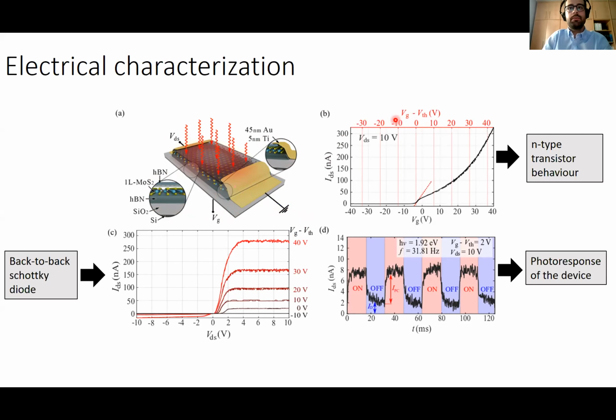In figure 1B, we observe the transfer curve of the device. We put here a fixed source-drain voltage, and we apply different back-gate voltages through the silicon that acts as the gate. And here we observe a clear N-type transistor behavior. When the back-gate voltage goes over the threshold voltage, we have a very high increase of the conductivity.